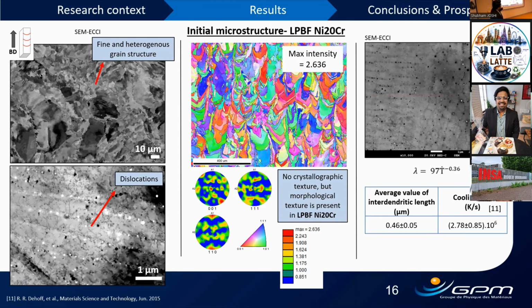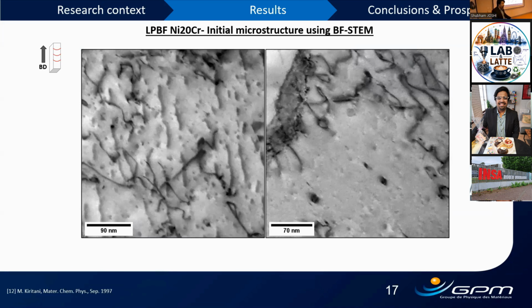Talking more about the dendrites or dendritic cellular structures, we can see these structures here, and we can see some oxides on the walls, and we also see some dislocations going through the walls and also crossing these dendritic structures. Because we're really interested in the dislocations which are formed in the as-built structure, we decided to investigate in detail via bright field STEM.